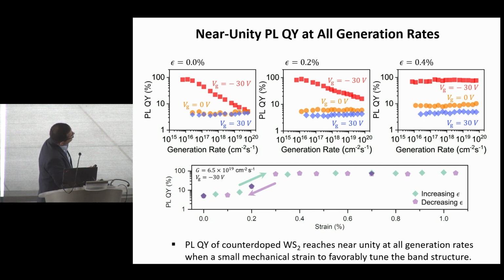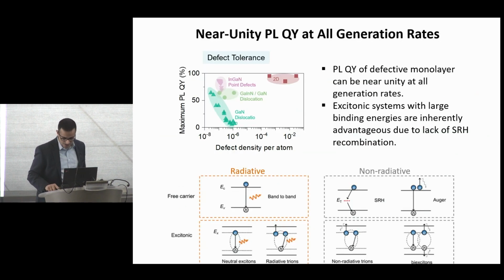And what we have been able to show more recently is that by applying strain, just mechanical strain, by doing strain engineering, we can actually dramatically reduce the exciton-exciton annihilation so that the material is bright even at very high generation rates.